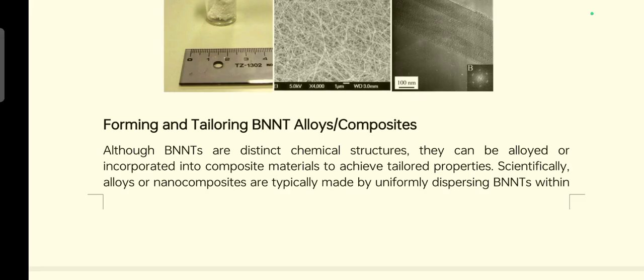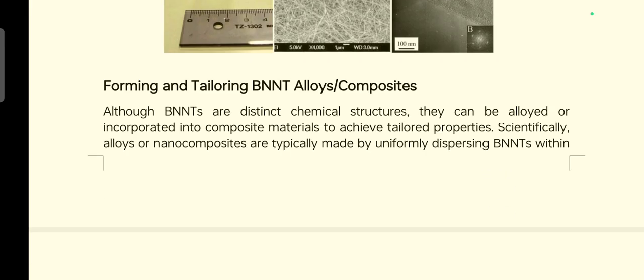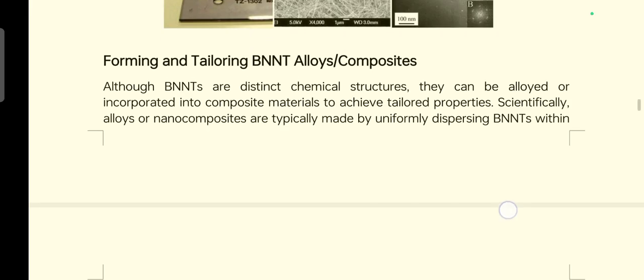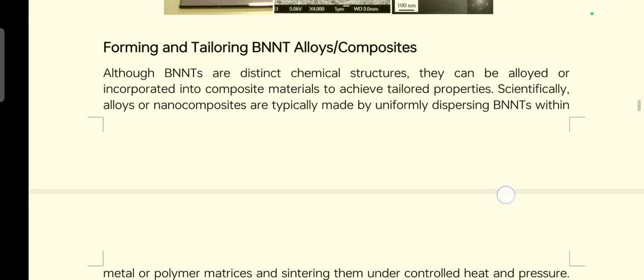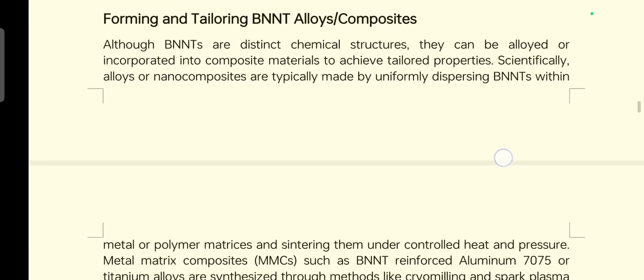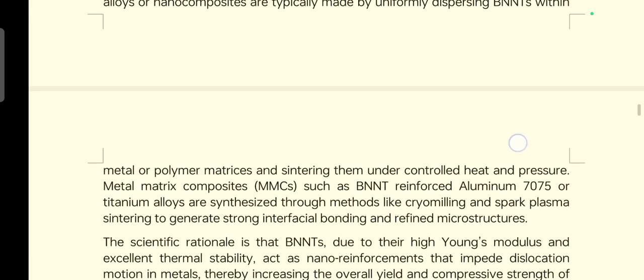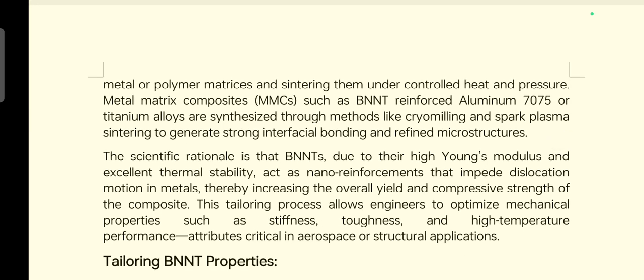Here we will also discuss the forming and tailoring of boron nitride nanotubes, alloys, and composites. Although boron nitride nanotubes are distinct chemical structures, they can also be alloyed or incorporated into composite materials to achieve tailored properties. Scientifically, alloys or nanocomposites are typically made by uniformly dispersing boron nitride nanotubes within metal or polymer matrices and sintering them under controlled heat and pressure. Metal matrix composites such as boron nitride nanotube reinforced aluminum 7075 or titanium alloys are synthesized through methods like cryomilling and spark plasma sintering to generate strong interfacial bonding and refined microstructure.